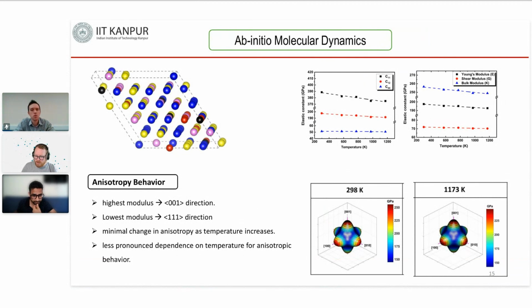And now the final question from Pulami. Are homogenization treatment and heat treatment at 1673 Kelvin different? Yeah. For homogenization annealing, we did it at 1000 degrees Celsius for 24 hours, and for checking the phase stability, we did it at 1400 degrees Celsius for 48 hours.